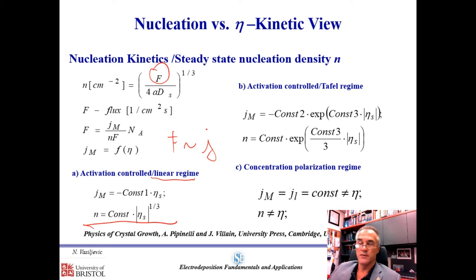Yet, when we are talking about the Tafel regime of the Butler-Volmer equation, which means exponential dependence of the current with respect to the overpotential, it is easily shown that nucleation density is also exponentially dependent on the overpotential. In the concentration polarization regime, we don't have a function that clearly links the overpotential to the nucleation density.